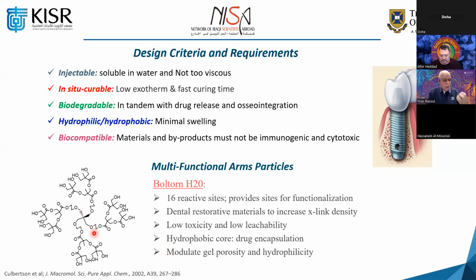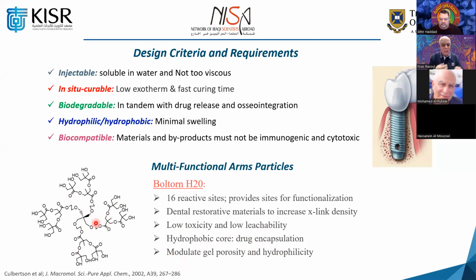It is hydrophobic in nature, which means if we have a drug like the one I showed you, it can be encapsulated easily into that. So it is a hydrophobic type of core. You could encapsulate your drug. And also you will be able to use it to modulate the porosity as well as the hydrophobicity or hydrophilicity of your hydrogel. If you incorporate this, you probably reduce the swelling as well as improve the degradation rate.